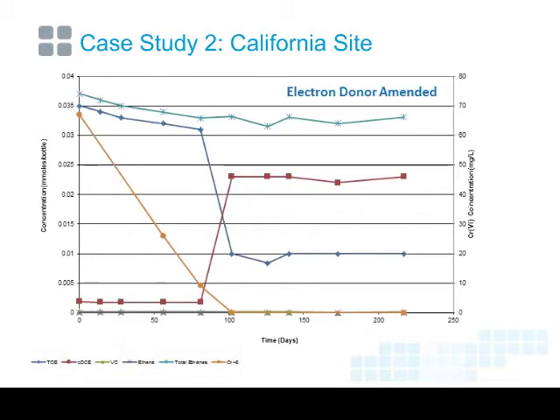The electron donor treatment shows very clearly we get some degradation with the amendment of electron donor. What we see is hexavalent chromium dropping out pretty rapidly by day 100, and that we see TCE, once the hexavalent chromium was significantly reduced, we saw TCE being degraded to cis-DCE. But then after day 100, for the next 100 plus days, we didn't see anything happen.